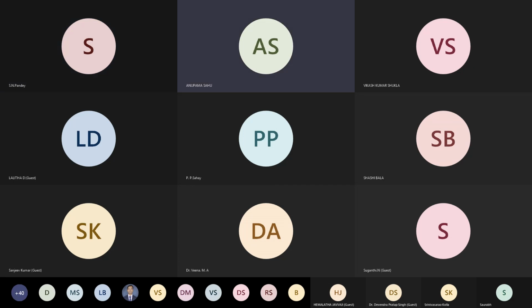So what do we have to do? We will have to either put in some carbon, some composite, something you prepare. And as far as you are telling about the porosity, if your electrode material is porous, the specific surface area is more. That will favor the electrochemical redox reaction. And with porosity, the electrolyte ions will easily diffuse. So the porosity as well as the electrical conductivity of the electrode material will favor the electrochemical performance. Might be one may hinder the other, but we will have to optimize in such a fashion. It is just like a trade-off between electrical conductivity and porosity.